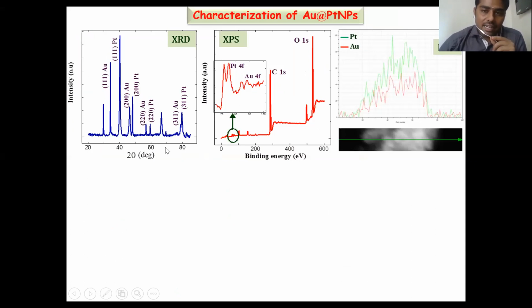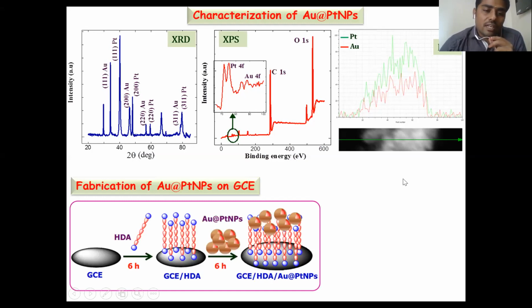Further, the formed gold platinum bimetallic nanoparticles were confirmed by XRD and XPS analysis. The XRD pattern shows the individual planes of gold and platinum, confirming there is no formation of alloy, but there is formation of core shell nanoparticles, so that we can get the individual planes. The XPS also shows the individual peaks of Au 4f and Pt 4f regions of gold and platinum nanoparticles. The EDS line scanning analysis also gives 2 separated lines for platinum as well as gold, meaning that they were not mixed as an alloy, and they have separated as gold platinum in the form of core shell nanoparticles.